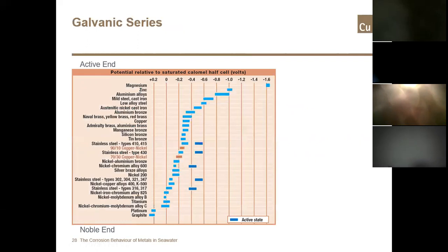But the further apart the materials are on this scale, the higher the rates of corrosion on the anodic material. So you can see that magnesium, zinc and aluminium on the table are all active galvanically and would be susceptible to corrosion if they were coupled with something at the more noble end of the scale, such as a bronze or a nickel alloy or titanium. So in that instance, galvanic protection would be necessary.